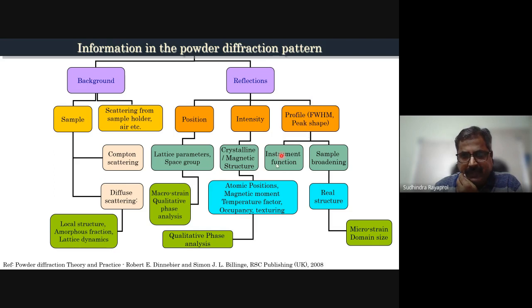The profile can be from the instrument function. It depends on which instrument you are using, or it can also be from the sample. So if you are working on nanostructured samples, you will see that the instrumental function becomes very important. The peak shape changes, the width of the Bragg peak increases. And if you can model that, you can actually understand the microstrain or the domain size. So we'll take some examples which will deal with all this in our next class when we do the tutorial.